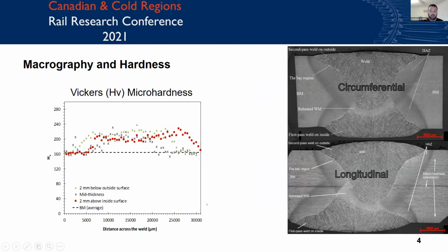So on the right-hand side of the screen, you can see the macrographs of longitudinal and circumferential welds that we studied, and they show the typical attributes of a two-pass submerged arc weld. You can see the two weld regions, the heat affected zones, and a small amount of reheated weld metal in the first pass. We conducted Vickers micro-hardness tests across these welds through the center and 2 millimeters below the inside and outside surfaces.